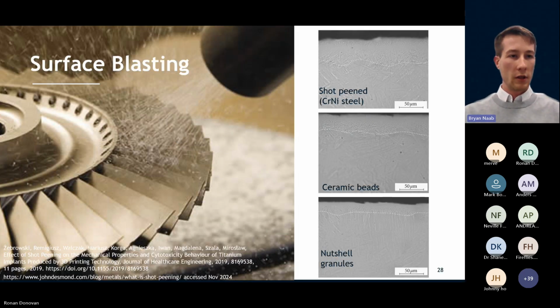Additionally, what we can do is surface blasting. We can blast with a number of different media, and depending on the type of media used will have a greater effect on mitigating fatigue. Essentially what this does is it creates a compressive layer on the surface, and fatigue requires a tensile component, so it will mitigate fatigue crack initiation on the surface.